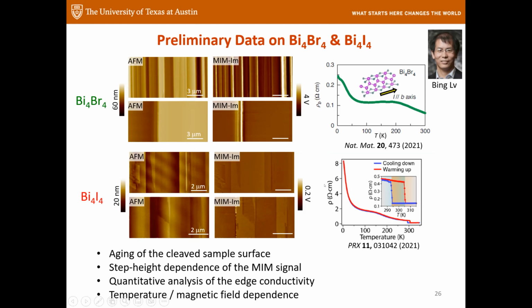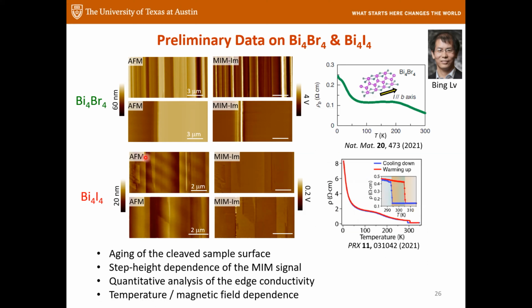Keji, there is one point here. The bismuth iodide side surface has a much smaller gap compared to the bismuth bromide. That might affect the observation here, but I'm not sure. I'm just pointing out some fact. At the end of the day, even the hinge states are different. Yes, the profiles are different, but the most important thing is that they do exist, but the surface gap is smaller for bismuth iodide, on the side surface.